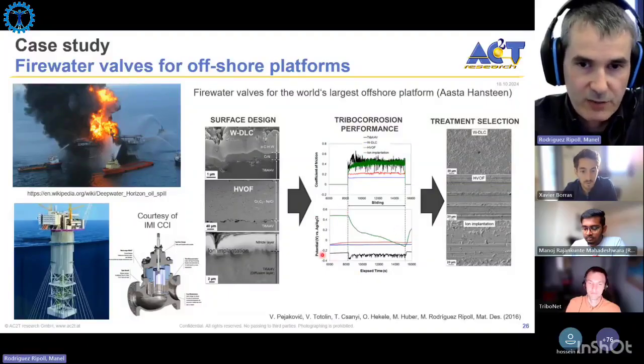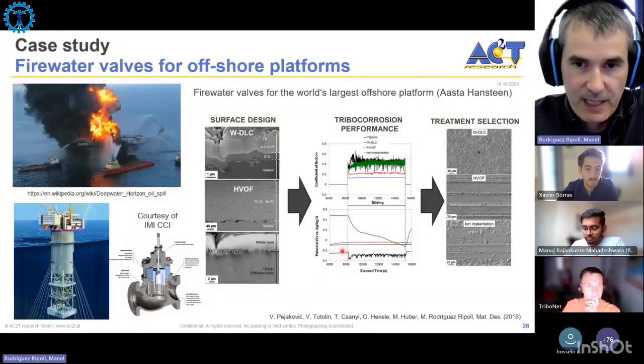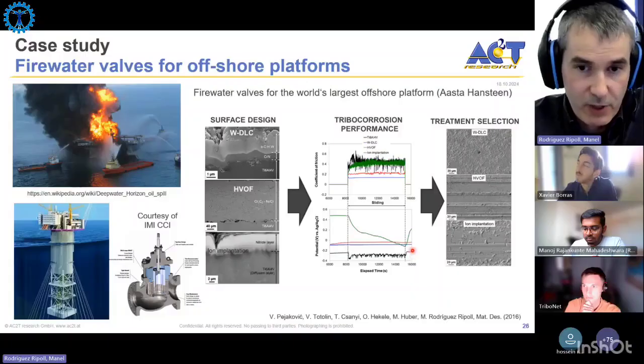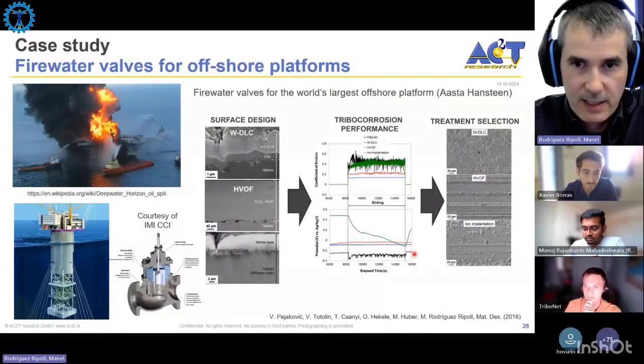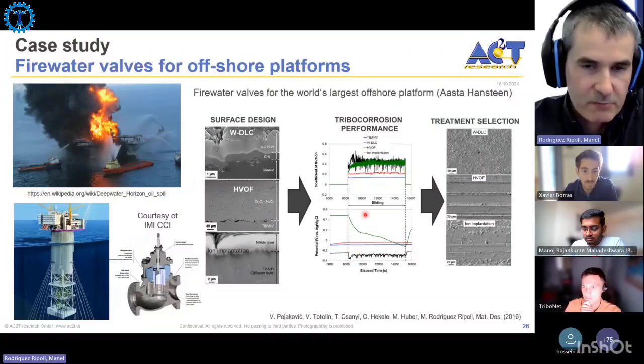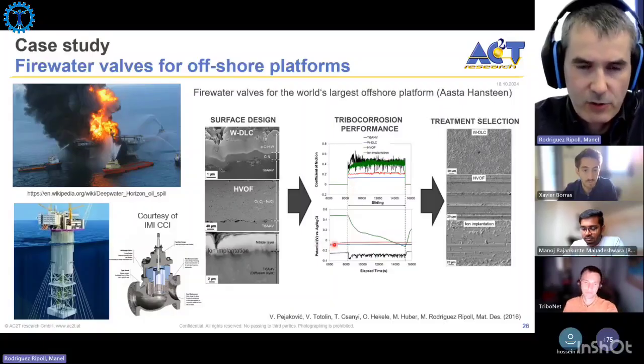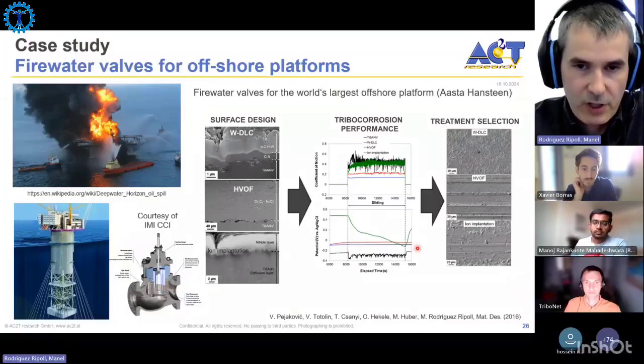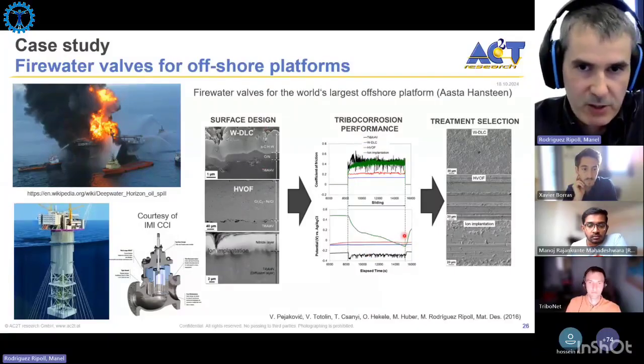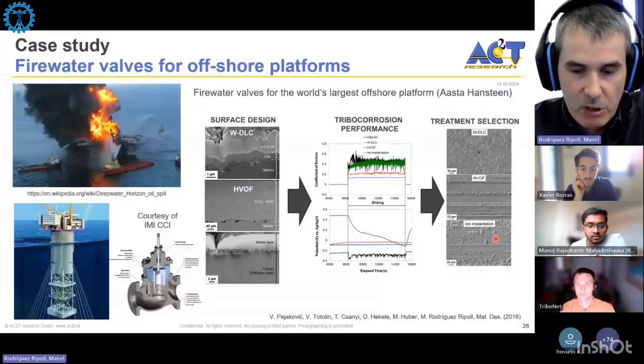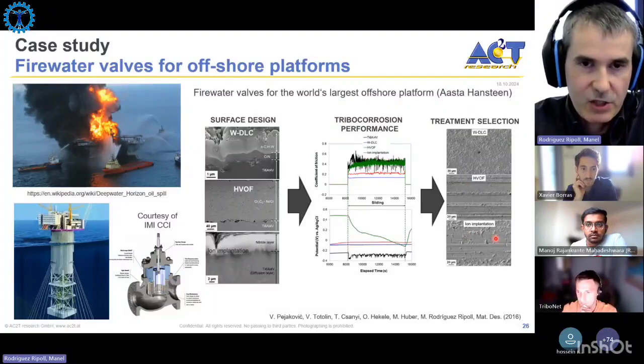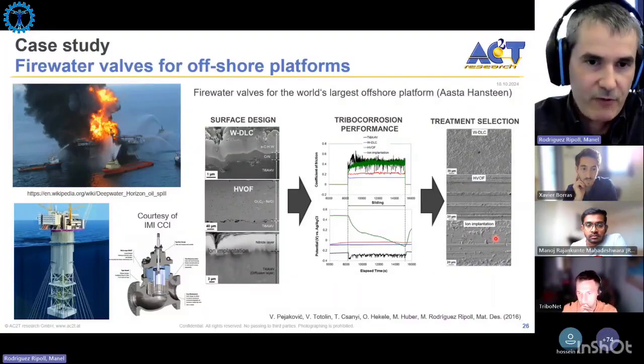With titanium 6,4, you see that the OCP at the beginning and at the end of the experiment is the same. And what you can observe for the thermal spray coating and the DLC, at these investigated low contact pressures that were relatively small, is that we were using a ball with 50 millinewton contact load. We can see here that there is basically no change in open circuit potential, indicating that there is no change in the surface condition of these two surface treatments during the experiment. Based on this information and the total removed wear volume, you can get this data for making a decision on which material can have the best tribocorrosion performance.